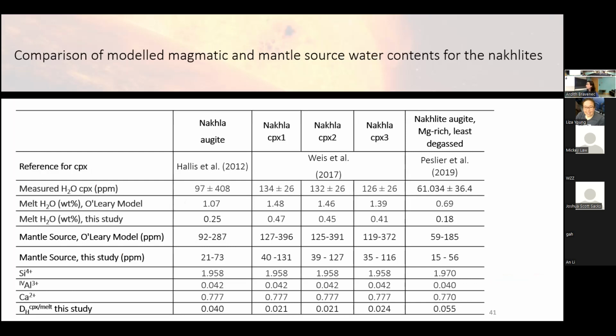So fortunately, some other workers have already characterized the clinopyroxenes in these meteorites, where we have several different analyses done on different grains. And then applying the model to it, we can back calculate that original magmatic water content. And for my study, I've done the 2-parameter approach. Both the magmatic water and the aluminum were taken into consideration, where previous models perhaps have only used aluminum. And we do indeed see a large difference there. And I'm going to talk about this more in just a second, but we can use those magmatic water contents to then back calculate the mantle source water.